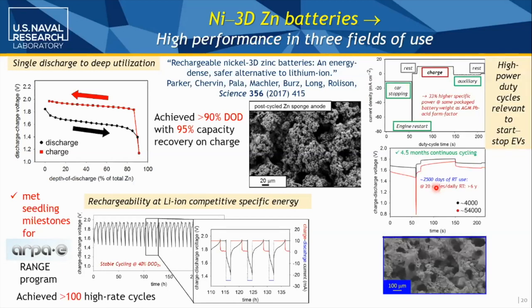But we also wanted to look at another potential application space, and that's start-stop micro hybrids. And that's typically showing up in your more expensive cars, particularly in Europe, because sometimes you have to sit at a stoplight for 2 minutes and everything shuts off. So you need an engine restart and plus all these other things you're doing while the car's running. So most people don't publish operational duty cycles, even the military, but BMW published theirs. So we scaled it to the cell we were working with, commercially harvested nickel cathodes versus our sponge, and set that up, and it went for 4.5 months. So on the nominally 20 cycles per day, that would have gone for 6 years.